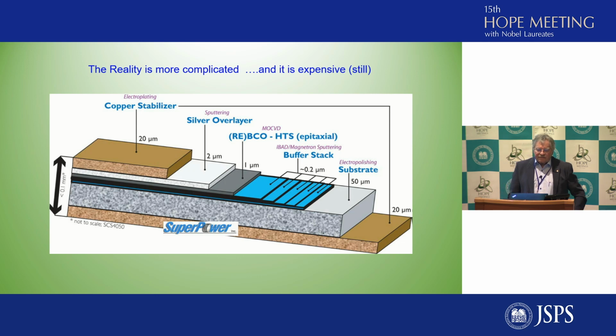So the reality, however, is more complicated. This is an example from a company producing these composites by different treatments. You have the substrate, that's here. You have the protection layer from one side, that's mostly copper. Then you have a lot of buffer layers in between with different deposition methods. And here, the most essential part, it's a superconductor. It's only the order of microns.